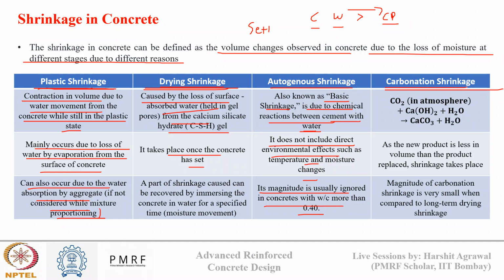And the final type is carbonation shrinkage. When CO2 reacts with calcium hydroxide, it forms CaCO3. We saw that in the lime cycle discussion also. Slaked lime upon reaction with CO2 forms calcium carbonate, and this new product has a lower volume compared to the reactant, which can lead to shrinkage. Such shrinkage is known as carbonation shrinkage, and these two, autogenous shrinkage and carbonation shrinkage, are much smaller compared to plastic shrinkage and drying shrinkage.